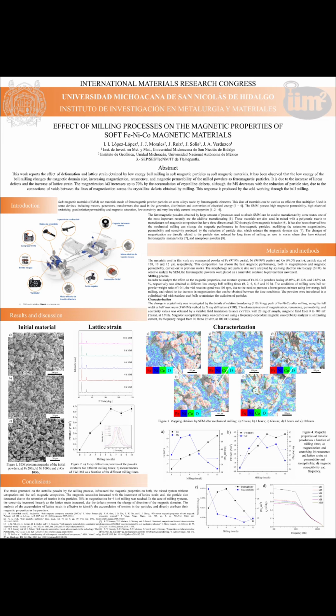A change of particle size or morphology has not been reported for any particular system in most cases. These effects tend to be related to mechanical milling modeling. Well, the flake-like morphology obtained in the present study is due to the centrifugal forces and the Coriolis effect between the wall of the vial and the milling balls carried out in one direction. This is for the 10 hours and 8 hours of milling.